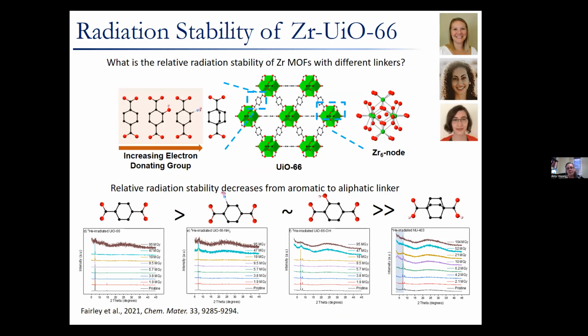So we've extended this to a zirconium MOF to look more at the paper I talked about earlier, and the radiation stability of the zirconium MOF. In this case, instead of changing the MOFs and therefore a lot of different parameters at once, we stuck with one MOF and then changed what the linker is. We looked at the normal BDC linker, and then we can functionalize it in two different ways, one by adding an OH group and one by adding an NH2 group, and then also looked at a linker that was aliphatic in nature as opposed to aromatic in nature. So therefore, we're looking at basically increasing the electron donating group on the linker.